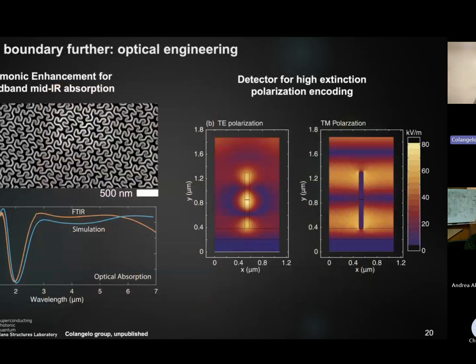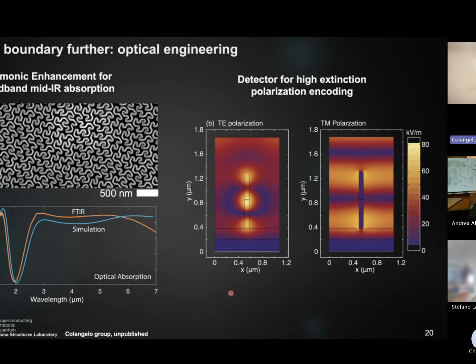And I want to conclude by saying that my group is also pushing a little bit further with the optical engineering by implementing plasmonic enhanced nanowires. Instead of using linear wires, we use fractal curves to be able to extend the broadband sensitivity of our wire. You can see it is flat from 2 to 7 micron. We're also working on polarization encoding by optimizing the absorption of the TE versus the TM mode, where the nanowire is placed here instead of the cavity. So this was an overview of what we do for high performance detectors for quantum information science.